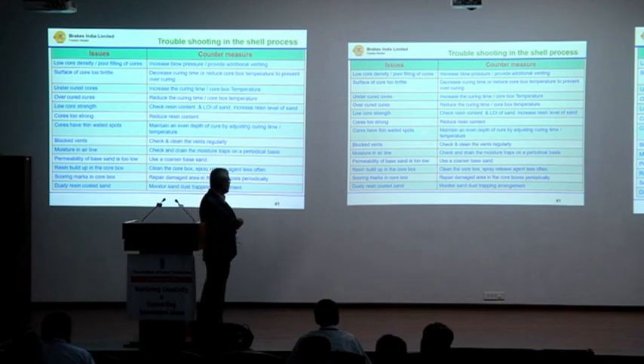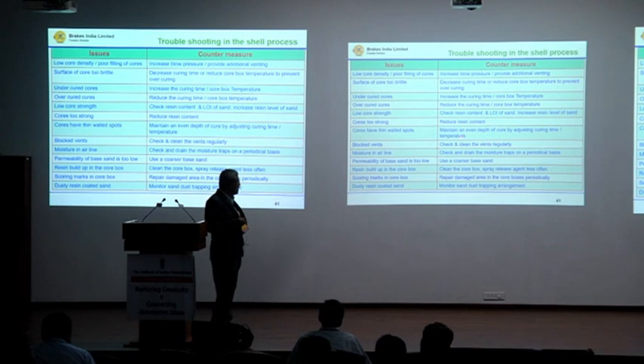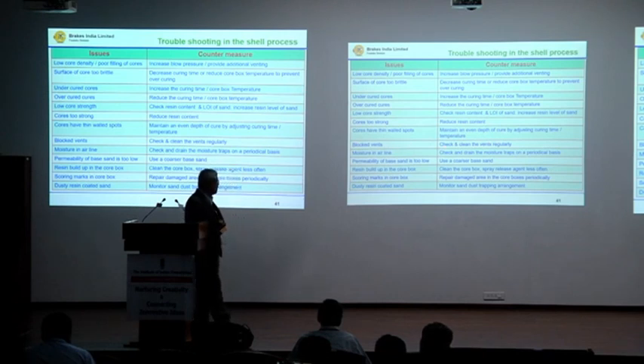For cores with thin-walled shapes, maintain an even depth of cure by adjusting curing time and temperature. For blocked vents, check and clean the vents regularly. For moisture in air, check the drains periodically.